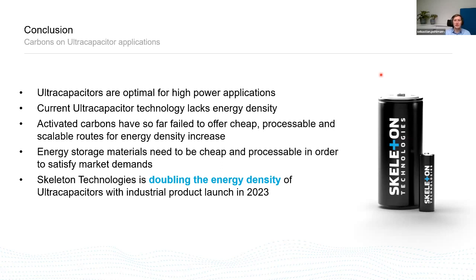Currently, supercapacitors definitely lack energy density, and they can be improved. That is true. But if you move there with activated carbon, so far the only thing that we have seen is that you always improve one property and lower the other ones. So you maybe improve gravimetric capacitance, but the volumetric capacitance is not increased, and it actually is lower. Or you increase both gravimetric and volumetric capacitance, but you have bad lifetime, or you have high cost, or you need to change your process, or the carbon becomes not processable by standard coating processes anymore. These are the kind of things that I, as an industry person, normally look at.